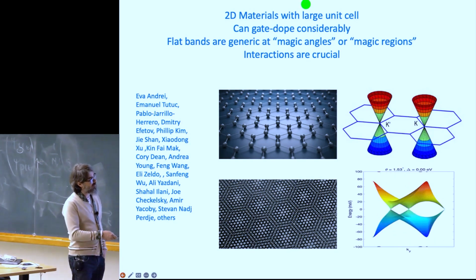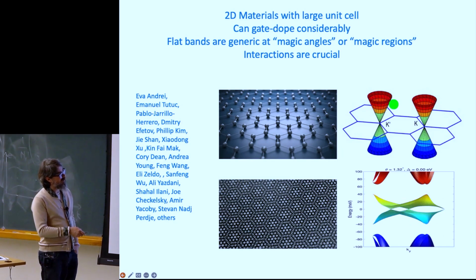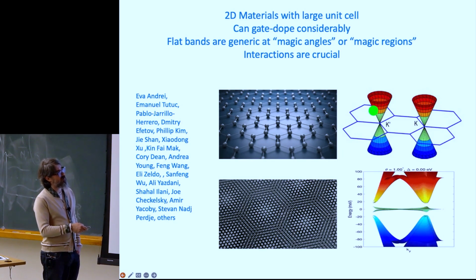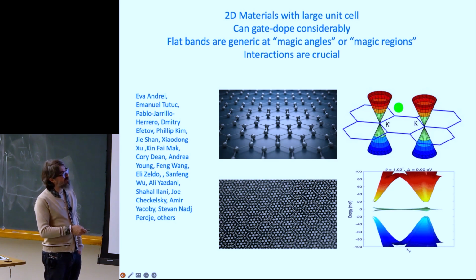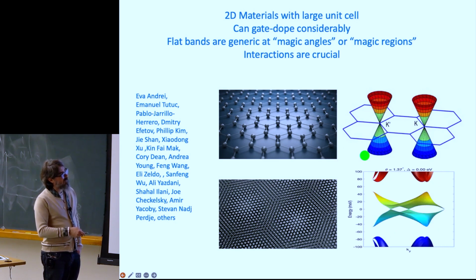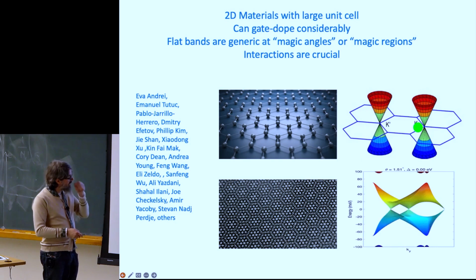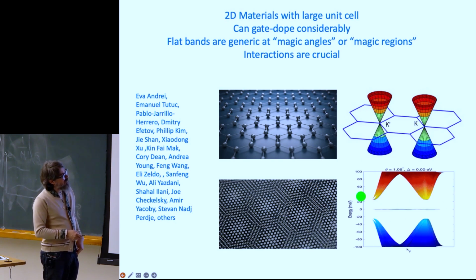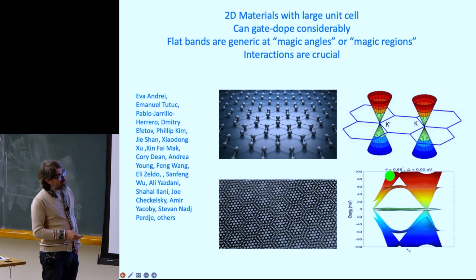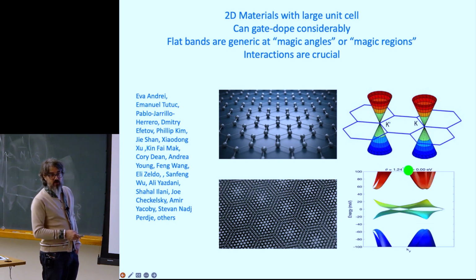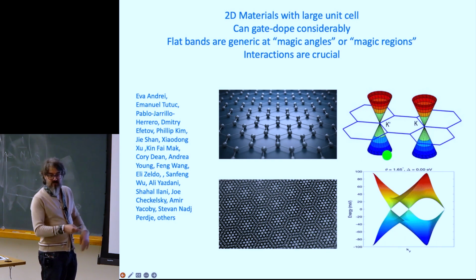Remember, graphene is carbon atoms with a bandwidth of, for example, if we go all the way here, 6 electron volts. So it's a large bandwidth. Our Dirac electrons are very dispersive. Take 2 layers and twist them by an angle, which you can see how small it is here, between 0.8 and 1.3 degrees. Just tiny.